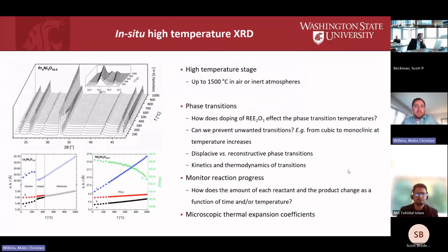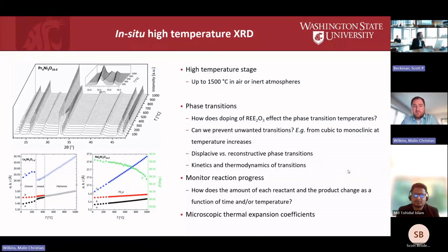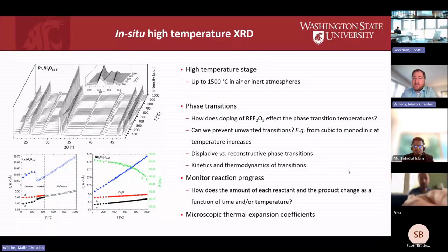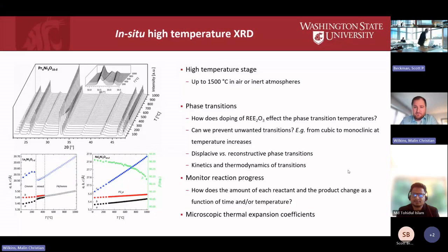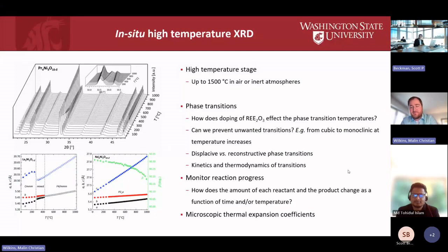I'll talk about the high-temperature XRD first. One of the things we're most interested in is phase transitions. Many rare earth sesquioxides have two, sometimes three or four phases at different temperatures. If there's a large change in density and structure as a function of temperature, the window won't survive. We can investigate questions like: how does doping cerium into europium affect the phase transition temperature? Can we prevent the unwanted transition to the monoclinic polymorph as temperature increases? We're also looking at more in-depth topics such as displacive versus reconstructive phase transitions, and kinetics — whether the phase transition happens slowly or rapidly at the temperatures we're examining.